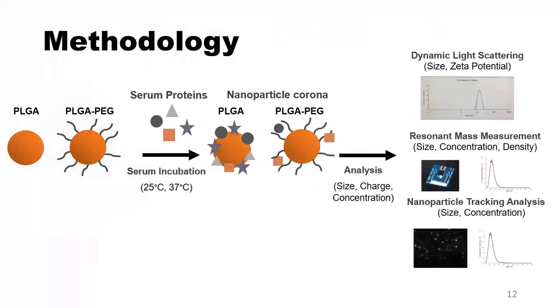So what have I actually done so far? We've taken PLGA and PLGA-PEG nanoparticles, incubated them in human or fetal bovine serum for between 0 and 24 hours at either 25 or 37 degrees Celsius, allowed them to develop a protein corona, and then gone on to analyse them using dynamic light scattering, nanoparticle tracking analysis, and resonant mass measurement.